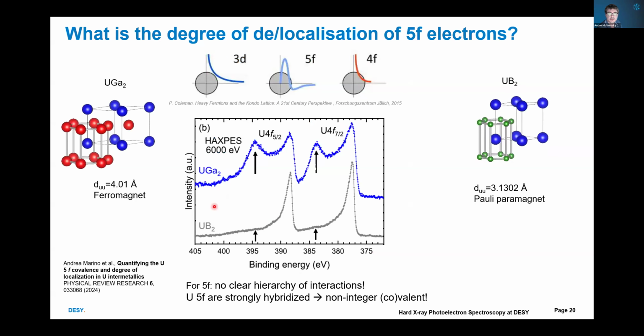But not all the experiments are so quick and easy. Here is one more example, about the degree of delocalization of 5f electrons in uranium compounds. People are always puzzled by the nature of f electrons in uranium compounds. They don't know whether they are delocalized as d states, or localized as f states. 5f electrons have kind of mixed valency. And we took two counterparts, a uranium gallium sample and a uranium boron sample, which have the same ground state symmetry, but two different lattice parameters.